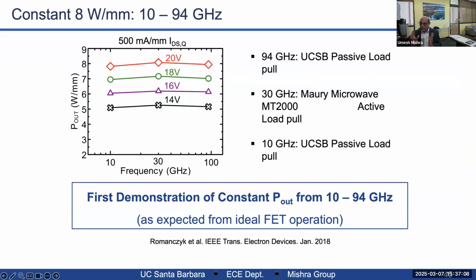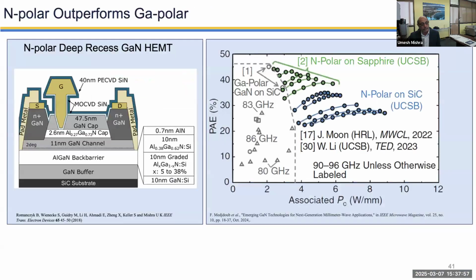This device is nearly perfect, not in an absolute sense, but as a FET, in the sense that the same device, this is Romanczyk's work, puts up the same watts per millimeter independent of frequency. At 10 gigahertz, it puts out 8 watts per millimeter. At 94 gigahertz, the same device puts out 8 watts per millimeter. This is important to recognize because this is the first demonstration of a device that puts out the same watts per millimeter independent of frequency. Watts per millimeter should never be a function of frequency. Watts is a function of frequency, of course, because of all the impedance matching you have to do, but not watts per millimeter.